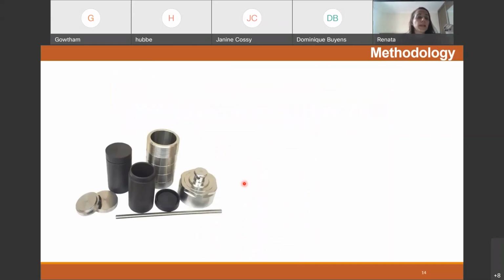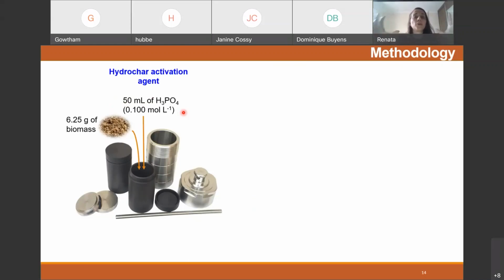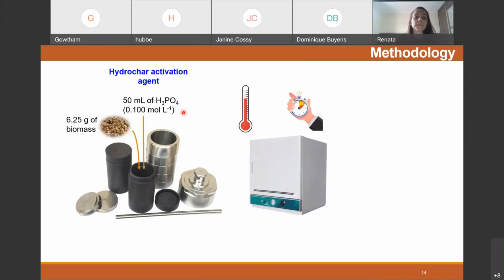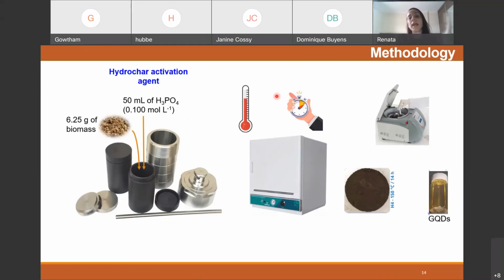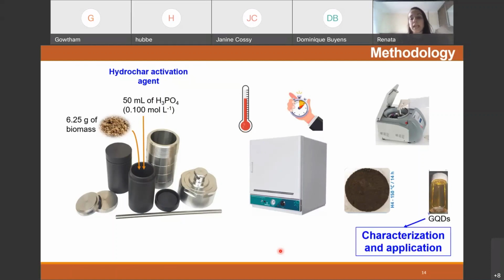To produce the materials, the biomass was added in the autoclave. We used 6.25 grams of the biomass, and we added 50 milliliters of phosphoric acid solution. This solution is important to activate the solid material, and is very important to the reactions that occur in the process. The system was stored in a stove at the temperature and the residence time selected previously. After, the material was centrifuged to separate the solid and the suspension. Finally, the material was characterized and applied in the photodegradation of methyl orange dye.